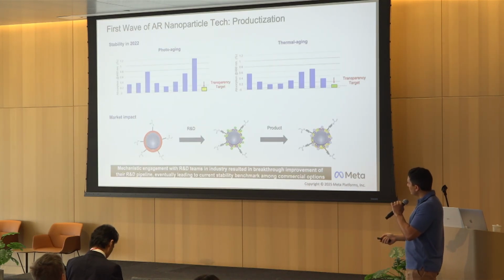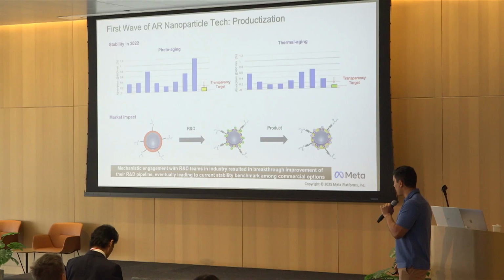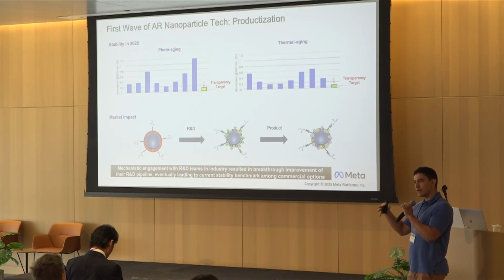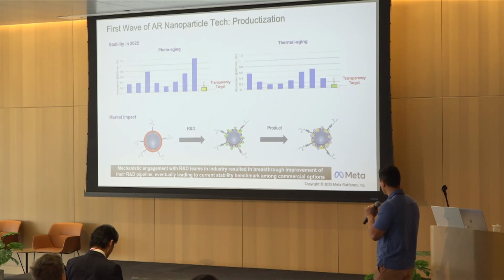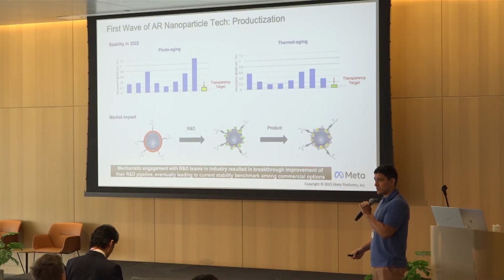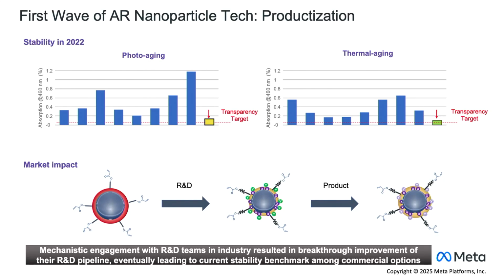So the result of that, about a couple of years ago, was that we demonstrated on an R&D scale this passivation approach for the highest refractive index nanoparticles that we have in the market. We make the most stable nanoparticles in the market at R&D scale and then transferred it to our development partners, and that material has been now commercialized last year. As far as I know, we use this material for some efforts, but many other people in the industry are now using it as well. So this is a nice example of the first iteration that our field has gone through in order to upgrade materials.